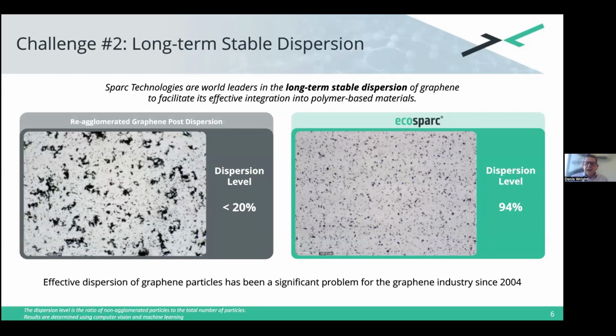So the long-term stable dispersion, picture on the left there, that picture on the left is agglomerated graphene. It's not happy. And if you put that into a coating and you couldn't tell that that's what it had done, and you did some corrosion testing on it, you would get terrible results. It probably wouldn't damage your results at all, but it would just be equivalent to what you would normally get for corrosion resistance or scribe creep out of the standard cyclic ISO 12944.